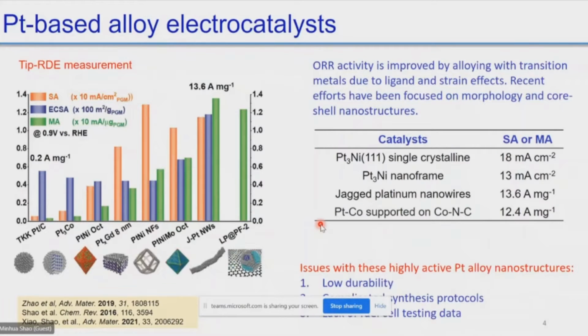Okay. So for the cathode reaction, there's the oxygen reduction. The benchmark is platinum supported on carbon black. So the mass activity at 0.9 volt is about 0.2 amp per milligram of platinum. By alloying platinum with transition metals like cobalt, nickel, iron, or copper, the mass activity can be enhanced, and the reason is due to the ligand and strain effects. Those transition metals are smaller, so it creates a compressive strain. Typically, if you're just using this alloy, the activity enhancement is limited to about 2 to 4 times.